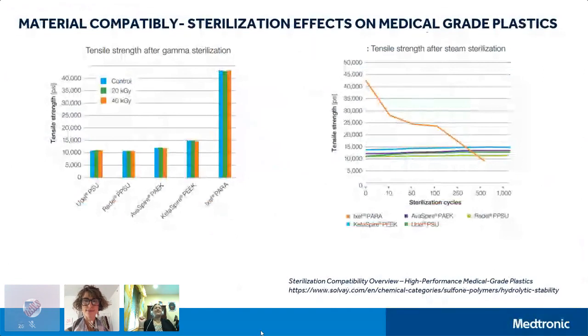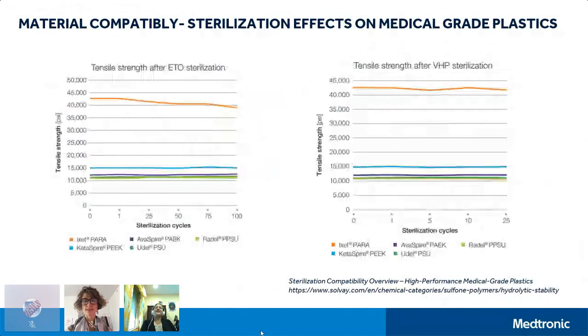Here is what we have, looking at some of the literature published on medical grade plastics, looking at the tensile strength after various doses of exposure. This is known, and this is what we have been using for making our portfolio. However, this is interesting and encouraging data on the right side, when you look at the tensile strength of some of the plastics after vapor phase sterilization. You could see that I can go up to 25 cycles on some of these without a decrease in the tensile strength. That is encouraging news, but it is only on a certain set of materials.